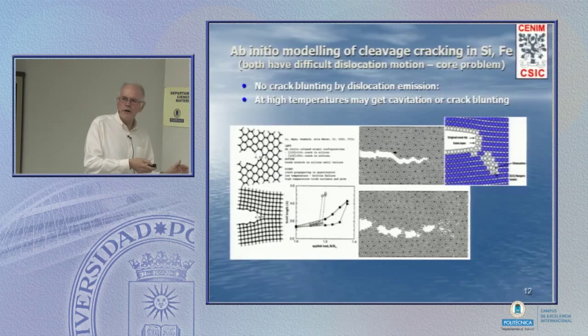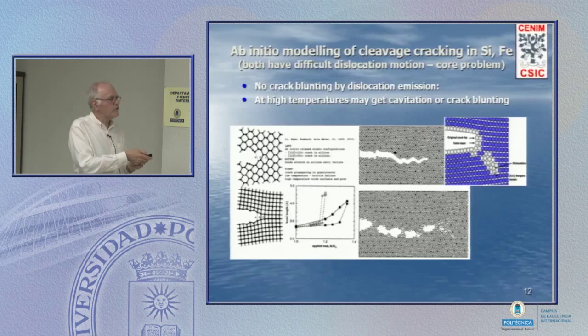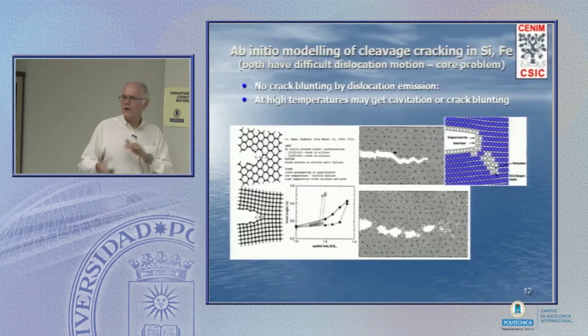If we want to go from really brittle to being somewhat or more and more ductile, what we need to do from the crack tip is nucleate and shoot away, throw away a dislocation. Now if we can throw away a dislocation, we blunt the crack tip, it becomes more difficult to propagate further, we've increased the toughness, and eventually we become ductile. Now the Burgers vector was twice as high, something like that, so the energy is 4 times as high. Moving it away is difficult, and because it's difficult to nucleate and throw away, there's a risk of high strength, low ductility.